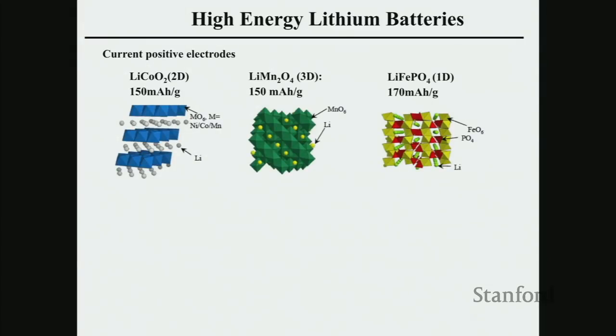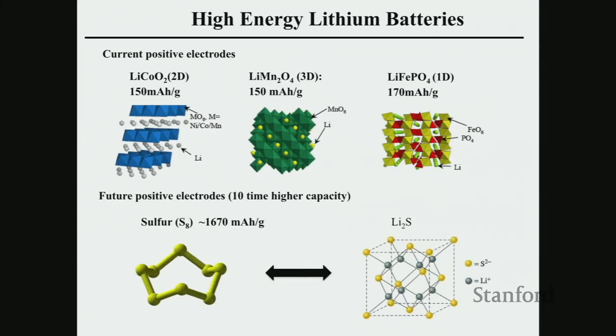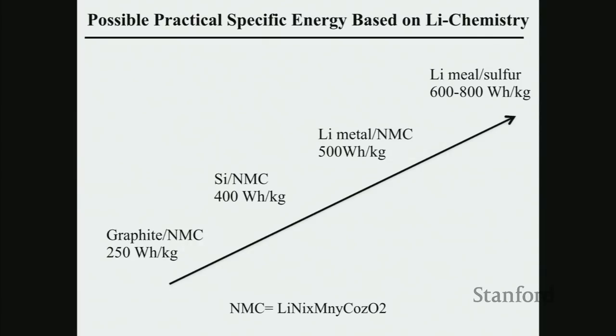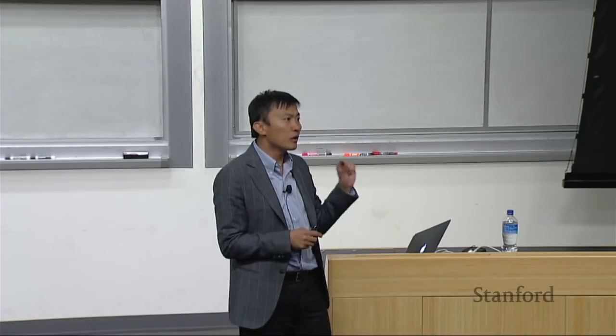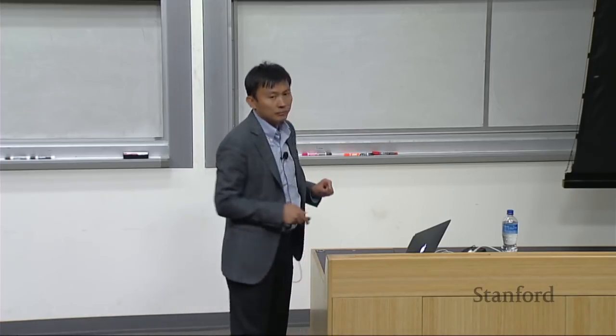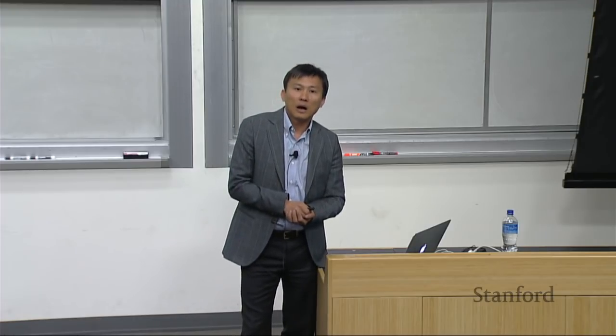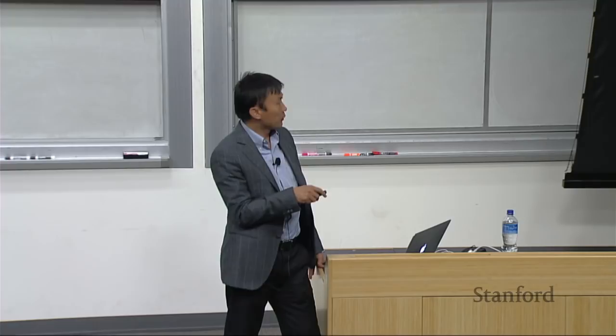For the cathode side, lithium cobalt oxide used in your cell phone, lithium manganese oxide, lithium iron phosphate. These have 2-dimensional, 3-dimensional, and 1-dimensional crystal structure channels for you to store lithium. That capacity also has a limit. They are not that high. New materials such as sulfur, becoming lithium sulfide, allow you to store also 10x. So this chemistry is really exciting. After about 10 years of research exploring broadly what types of chemistry are attractive for transportation and grid scale, if you're looking for a chemistry that can have practical, I'm mentioning practical, not theoretical, high energy, this might be the pathway we have to follow.